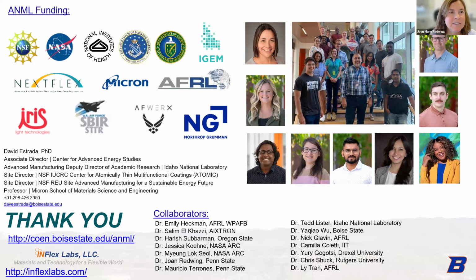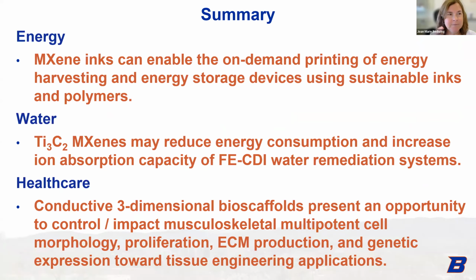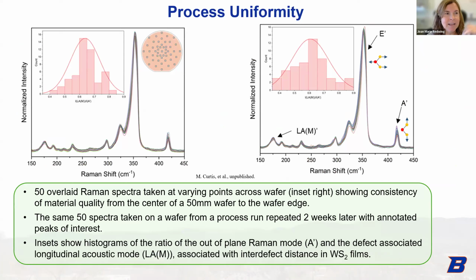I guess I could ask a question. So it looked like your uniformity was good across the three 2-inch wafers. Did you have to do any tweaking of the showerhead flows to optimize uniformity? No, I would say no. What we did see was the chalcogen to metal ratio plays a significant role in the quality of the film, of course. But uniformity was equally bad across the wafer, or equally good when we finally optimized the recipe. And one thing also, we did get all the way out to the wafer edge, within 1 millimeter, where we had really good quality film before we started to see less coalescence at the wafer edge.